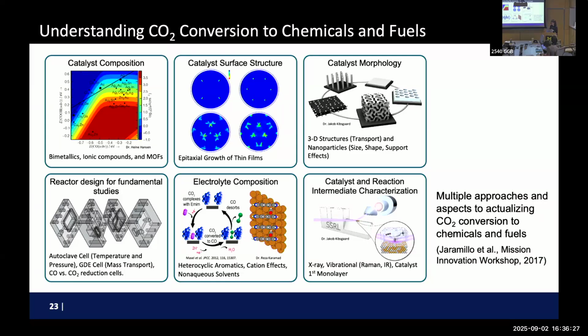So knowing that, I was curious. You just assume somehow or another CO2 will show up at the surface of a catalyst. But how is it going to get there? Because a lot of electrochemical systems use electrolyte, which is water-based. But CO2 solubility in water is not good. That's why we don't use water to capture CO2, right? So you paid a lot of energy to capture CO2 into pure form, and you try to bubble CO2 into the electrolyte, which has very poor solubility of CO2.